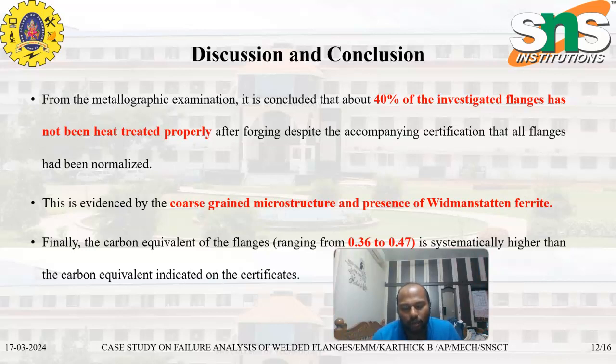When normalizing is done properly, the material is heated, held at a particular temperature, and cooled in still air, so that the cooling will be faster and fine grains will be formed. These fine grains in turn help to give high strength.